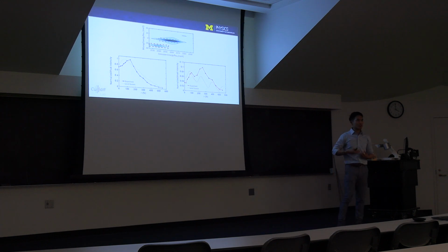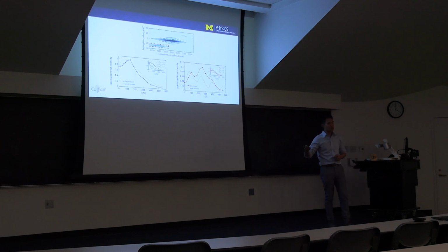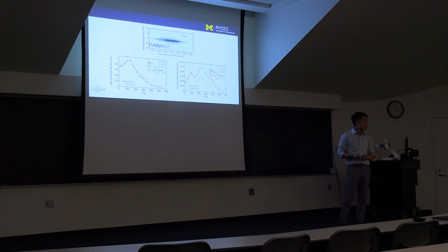We tried different things such as varying the Fröhlich phonon coupling strength, extending the dephasing time of the vibrationally excited interband coherences, and even simple non-Markovian dephasing models such as the Kubo line shape, but that didn't work. And we also tried incorporating the acoustic phonon dephasing using the parameters from the previous section, but even this didn't work.